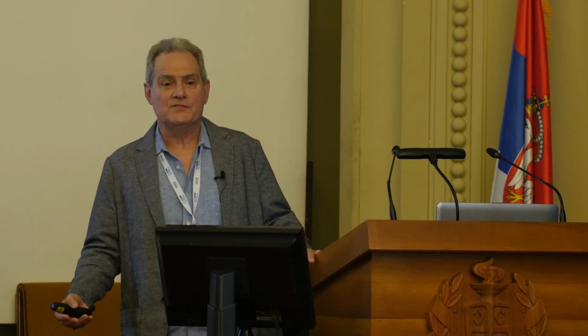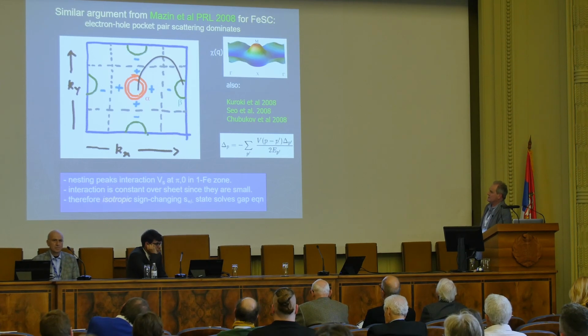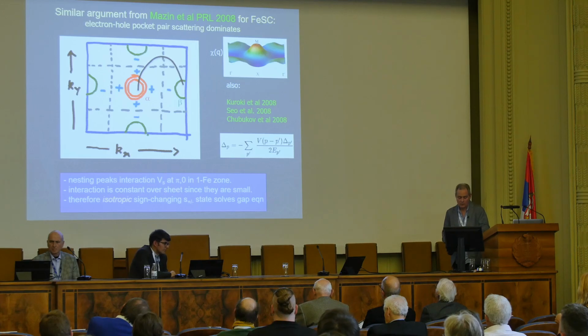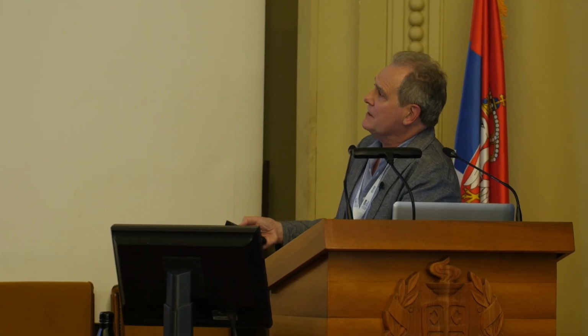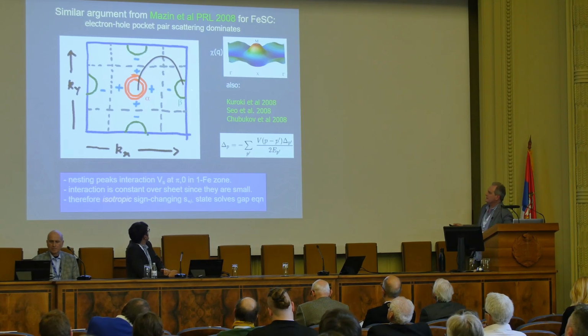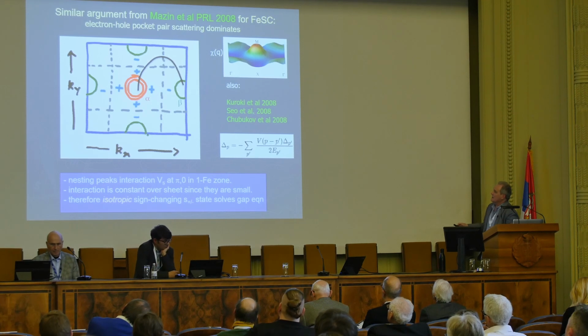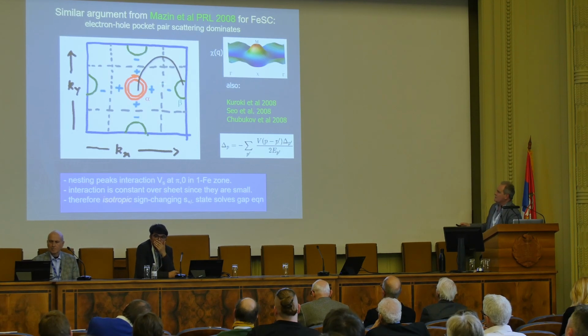So when these iron-based superconductors were discovered, people came along very rapidly and said, hey, I know how this spin fluctuation mechanism works. Let me do it, instead of for a cuprate Fermi surface, for this iron-based Fermi surface, which has small pockets centered on the high symmetry points of the Brillouin zone. Okay, and you see that these pockets nest rather well, and therefore there's going to be a peak in the susceptibility at this wave vector. And therefore the analogy is exactly as what I had before. You take that peak and you have to change the sign between the two pockets. And you get the so-called S plus minus state, which is thought to be characteristic of most iron-based superconductors.